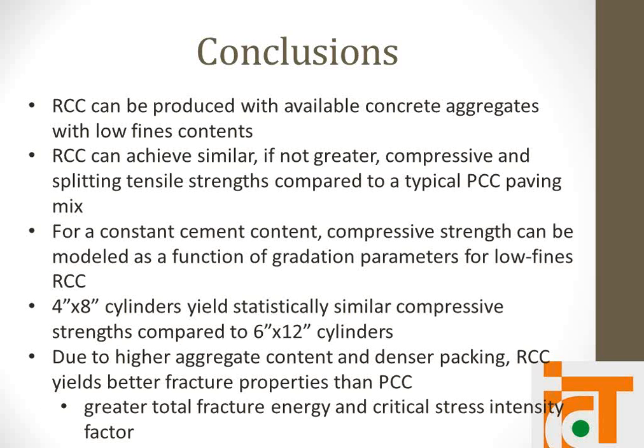So some of the conclusions that we can make are that we can use available concrete aggregates even though they have much lower fines contents than typically recommended. And it can achieve similar strengths to typical concrete, compressive and splitting tensile, but it is recommended that we either use a larger sample size or a greater factor of safety when designing due to RCC's tendency to have higher variation. And for a given cement content and for the aggregates used, we can predict the compressive strength just from the gradation parameters. And also, fracture properties are better for RCC than typical concrete due to the higher aggregate content and denser packing.